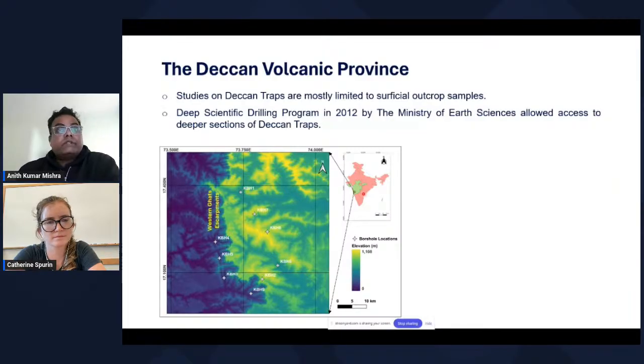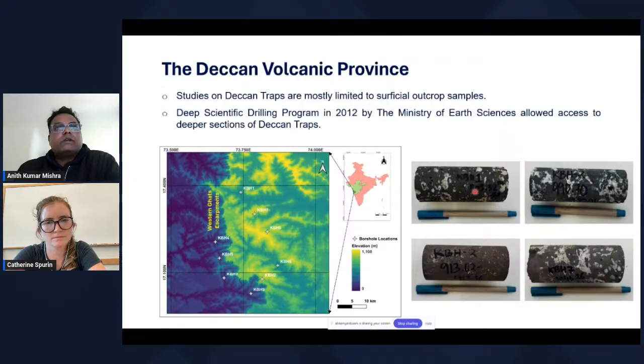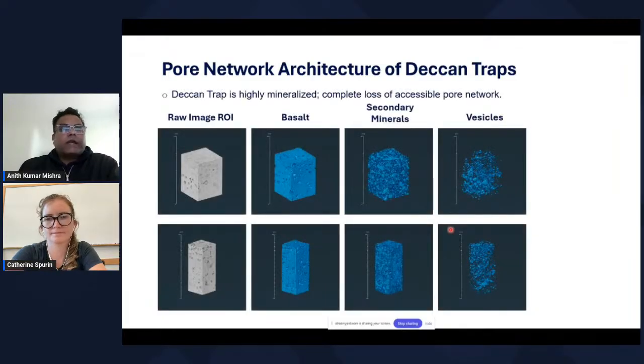And when we studied the core samples, what we saw is this. You can see that there are already pre-mineralized secondary minerals within the vesicles and the pore network of the Deccan Traps. Then we collected these core samples. We did micro CT scans to volumetrically render the different components. So this is the raw image. This is the volumetric portion of basalt. This is the portion occupied by secondary minerals. This is the vesicle network from 2 different samples. So these are the 2 different representative samples here.